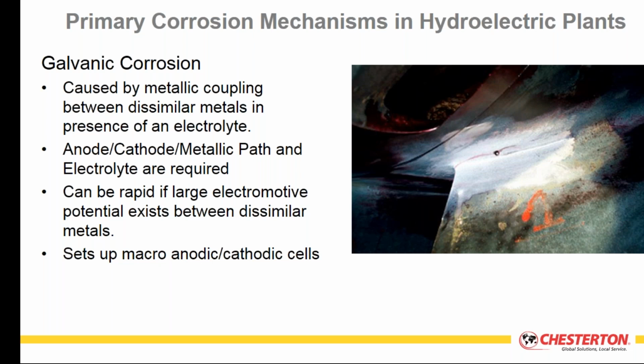In order for this to occur, it normally requires some type of conducting electrolyte. Water is a very convenient one. Obviously, the more acidic or higher ion concentrations you have in the water, the more rapid the rate of corrosion will be. Another area that is required is metal-to-metal contact, so you need to have these differing alloys in direct contact. They can't be separated by any type of dielectric insulator because there is an actual current flow occurring between the anode and the cathode. So in order for galvanic corrosion to occur, you need an anodic metal, a cathodic metal, a metallic path which is the metal-to-metal contact, and a conducting electrolyte.